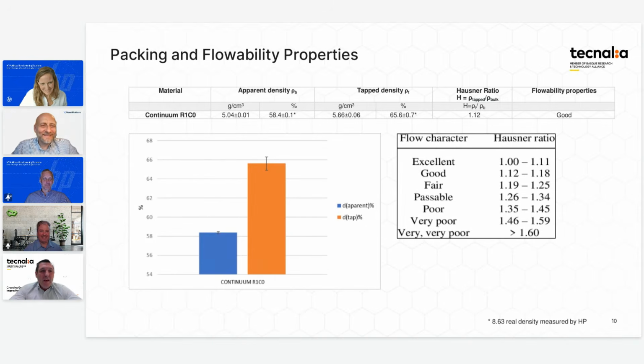Okay, so moving forward a bit, packing and flowing properties of the powder. Here you can see different data for the bulk or apparent density and the tap density. Those two parameters are very important if we want to have a high green density and controlled shrinkage during the sintering process. Here you can see that we have quite a nice tap density, around 65% of the theoretical density. That is a nice value, quite comparable to other typical binder jetting powders.